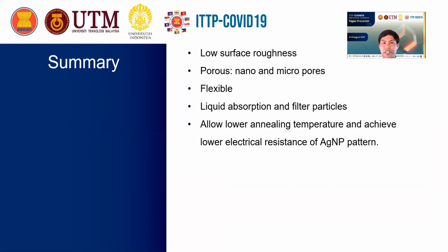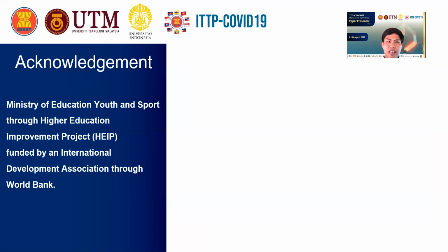So I would like to give the summary. We made a printing substrate with low surface roughness. It has a porous structure, it is flexible, and it can absorb liquid and filter nanoparticles on the top, and it can also achieve low electrical resistance after annealing.